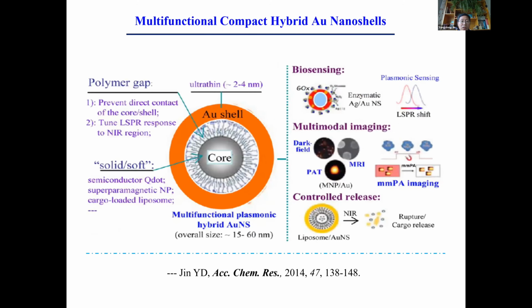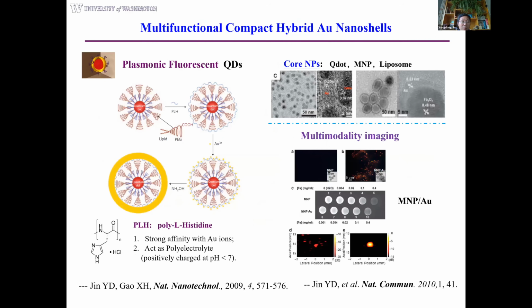Previously, our interest in plasmonic nanoparticles focused on preparing multifunctional compact gold nanoshell. Here shows a biomimetic method to prepare ultrathin gold nanoshell on the surface of core materials by using poly-L-histidine as a molecular template to control the deposition of gold film. Due to the presence of a polymer gap between the core and the shell, the fluorescence of the quantum dot can be preserved, so it can be prepared as a multimodality imaging nanoprobe. Also, the core material can be changed to magnetic nanoparticle and also soft liposome.